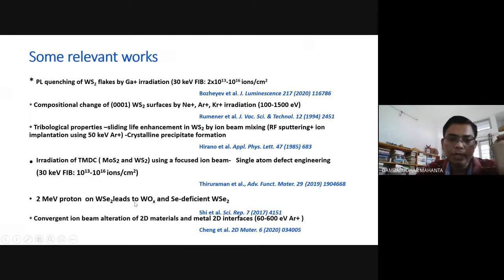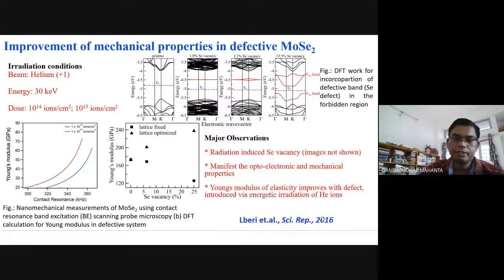Similarly, WSe2 can lead to WOx. Ox means when the composition is unpredictable. It could be 2, 3, 4, so changing. And this is because of the presence of defects. And selenium deficient WSe2. Then convergent ion beam alteration of 2D materials. So this is a very good article and very, very recent article. One can give a look. Alteration of 2D materials and metal 2D interfaces.